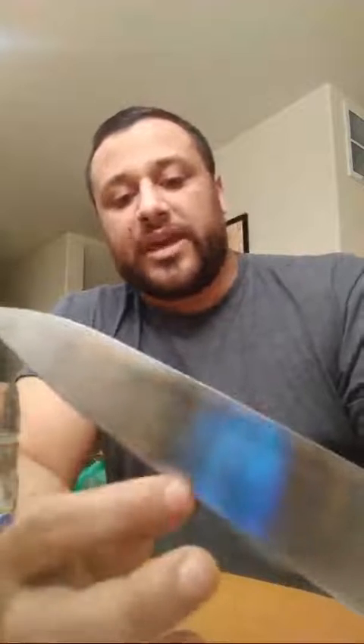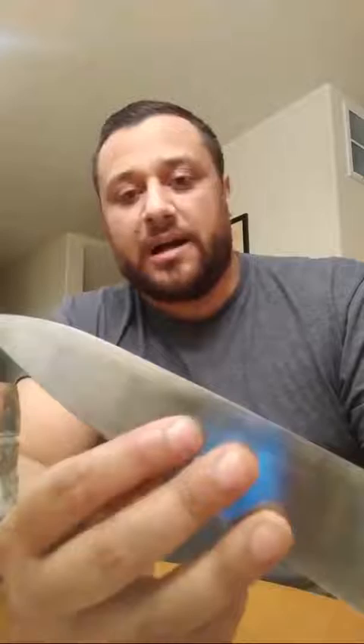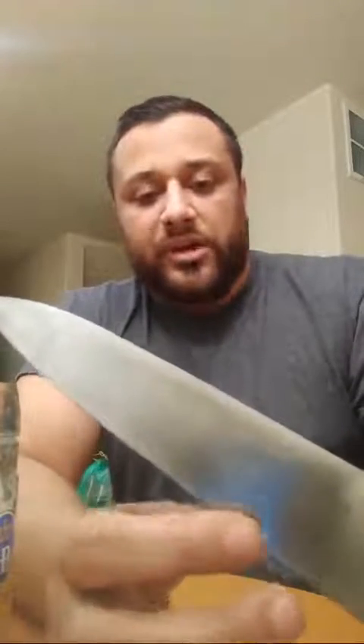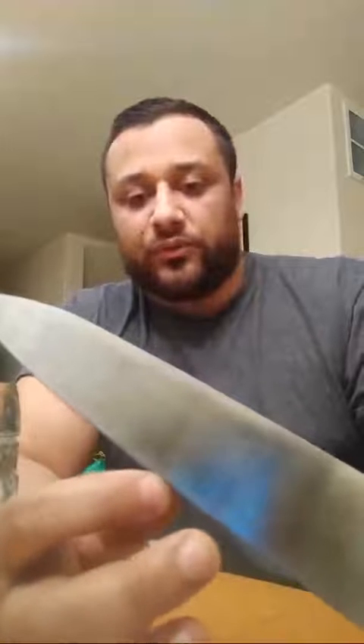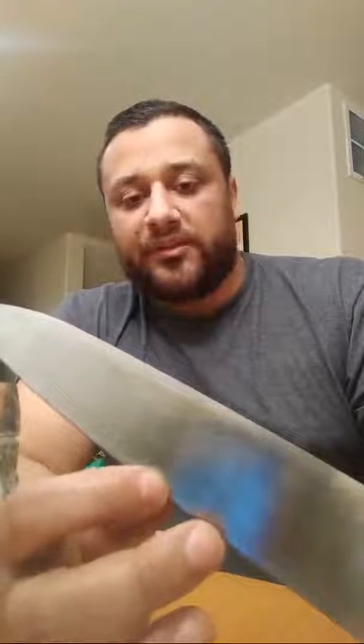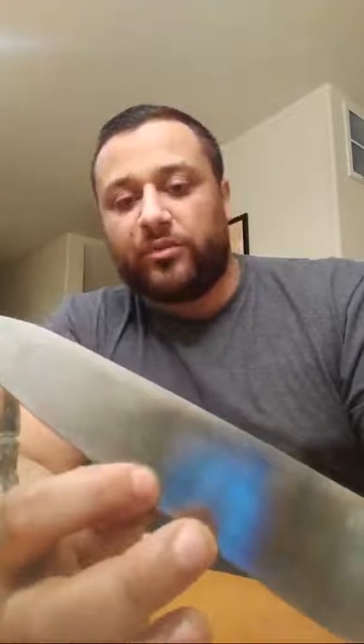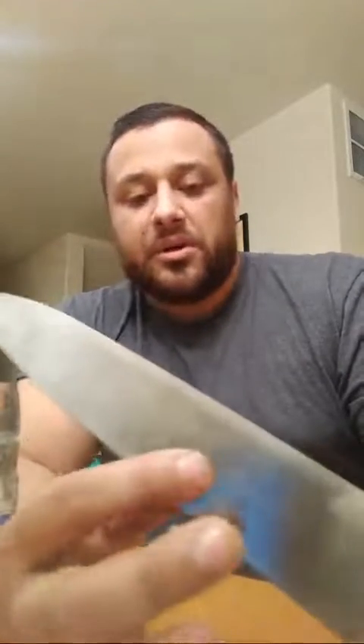I think the other problem you'd run into is galvanic corrosion, where you have different kinds of metal. You have a metal on top, chromium is a metal, and you have a metal underneath. And that can increase the potential for rust to form between the layers of chromium and steel. And so you would have it rust from the inside out.